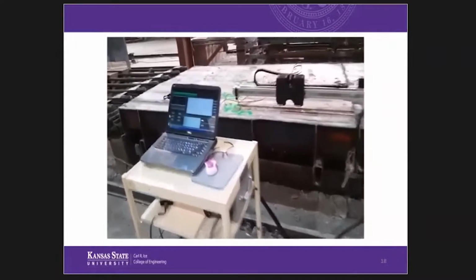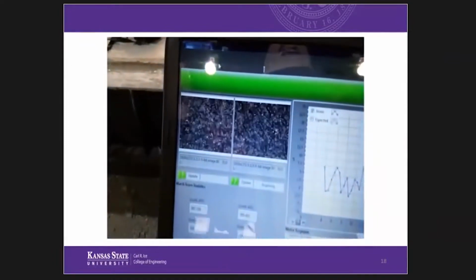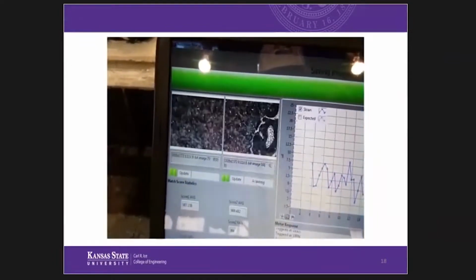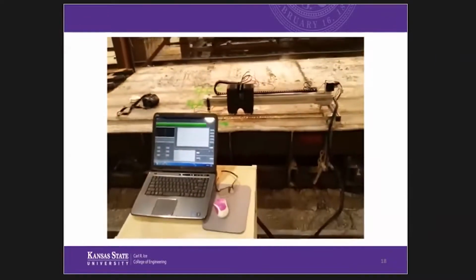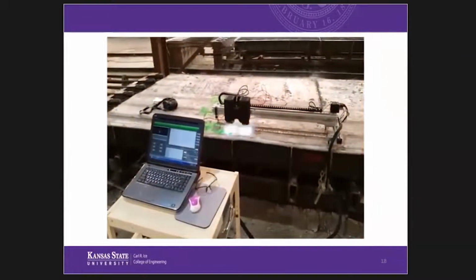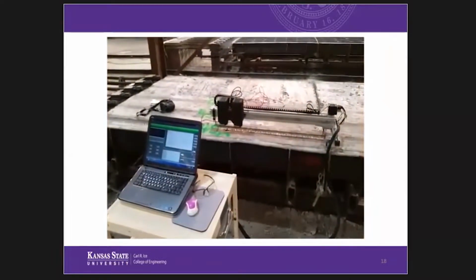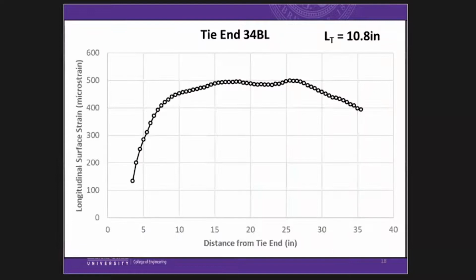So this takes automatic, we set that on a tie, and it takes two images captured exactly at the same time as it goes down. We set that on the tie before detensioning, and we come back after detensioning, reposition it, and we do image correlation of those pairs, and we come up with a strain profile. And the fact that the strain profile, the top portion kind of bumps up and down a little bit, that's because the ties go in and out. They actually have physical shape. It's not a prismatic tie. So we can actually measure the shape factor, scan the tie, and then correlate back. And this transfer length, in this case, 10.8 inches, that comes out automatically.